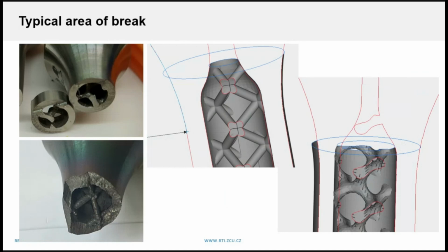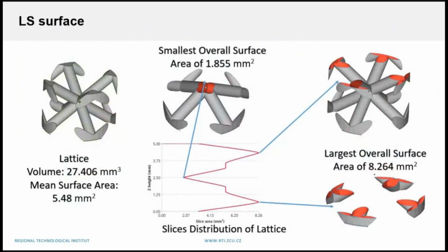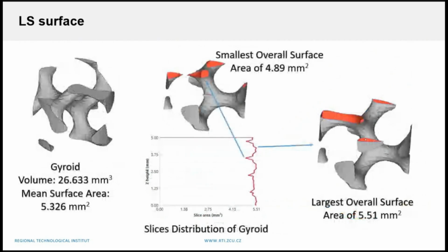Now we are analyzing the trouble areas on the basis of the process. We check the surface of the melting area, and in the case of the BCC structure, you could see that the melting area changes very quickly. So it means that the thermal process changes very quickly in this case. In the case of Gyroid, it is a little better. We can say it's close to constant.